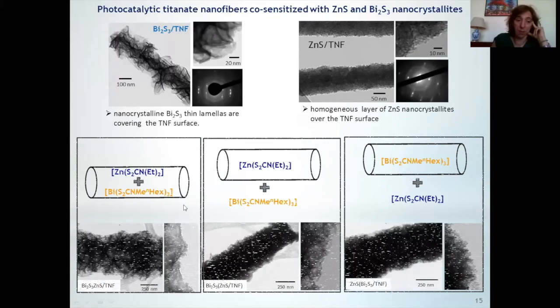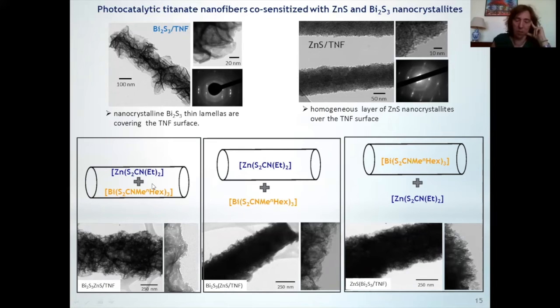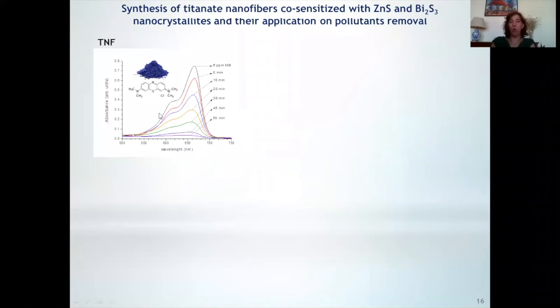We have done this and we decided to study the influence of the layout. So we decided to prepare zinc sulfide and bismuth sulfide nanoparticles at the same time. We decided to prepare first the zinc sulfide on the surface of the titanate and then put the bismuth sulfide, and do the opposite. Of course, here morphology can help us. For instance, in this case, it's visible that we have many more zinc sulfide nanocrystallites than we have here in this situation. All of these materials are photocatalytic, but I would like to show you the results about the combination of bismuth sulfide and zinc sulfide prepared at the same time.